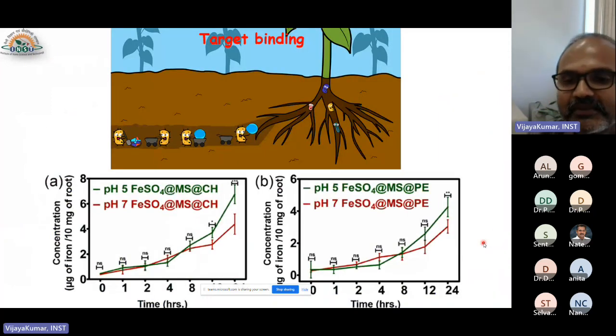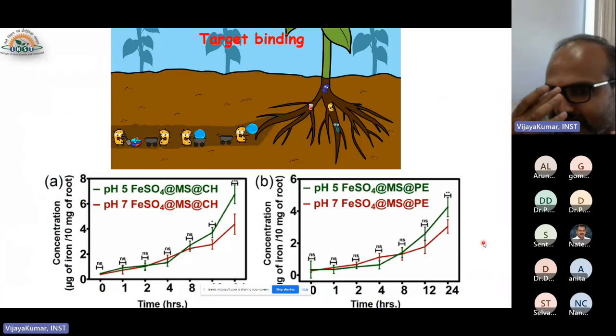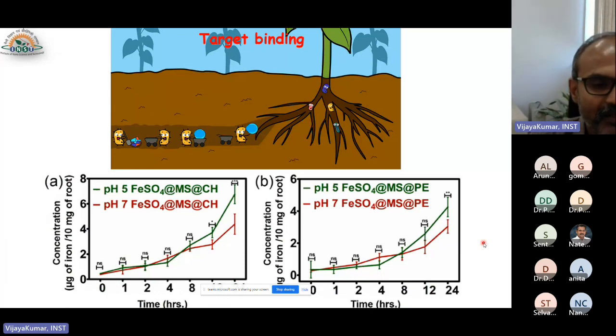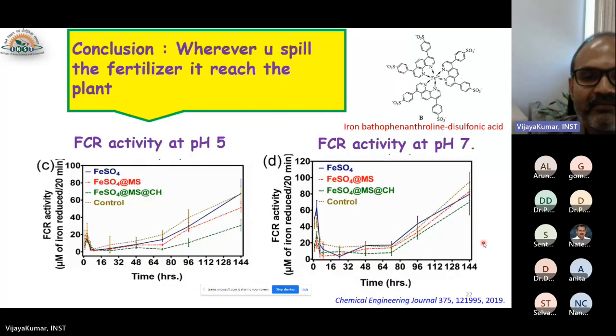Now the next one is whether these materials have very good binding with the root. The chitosan has a positively charged surface, so obviously it is expected to have more binding on the root. That is how we show that there is more binding on the root, and so more concentration of the iron in the root is happening. And finally,